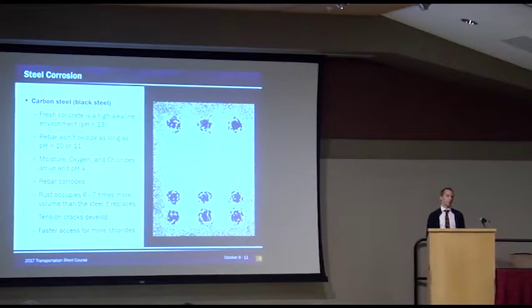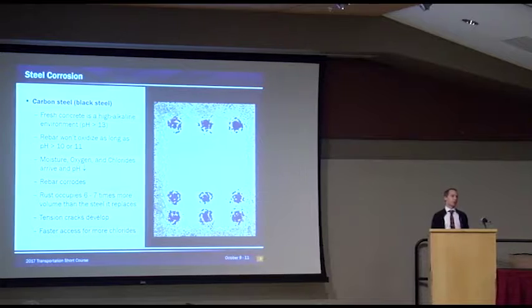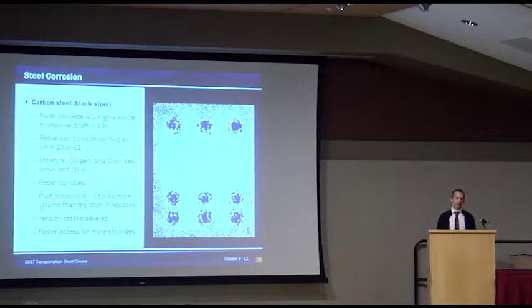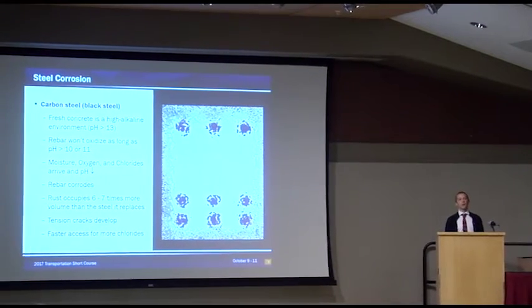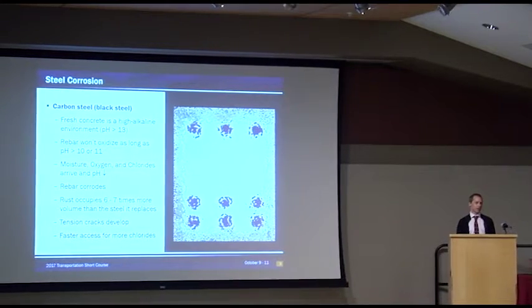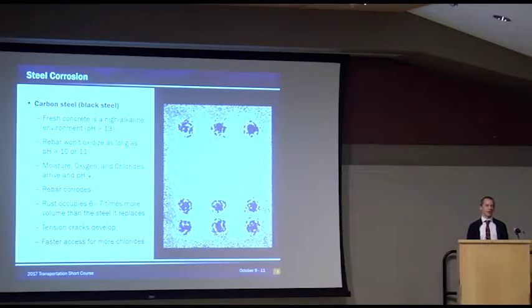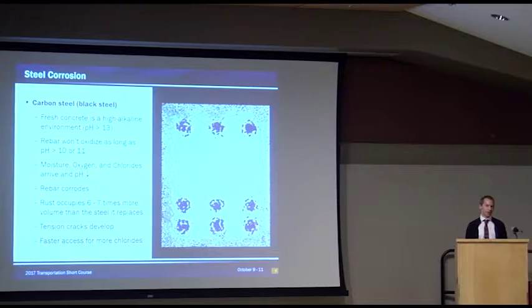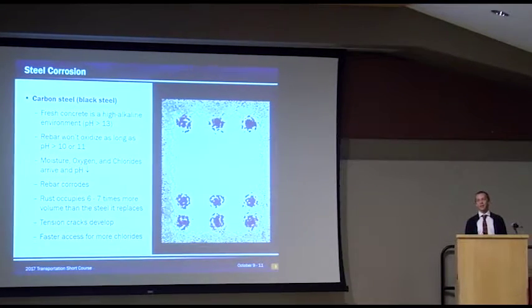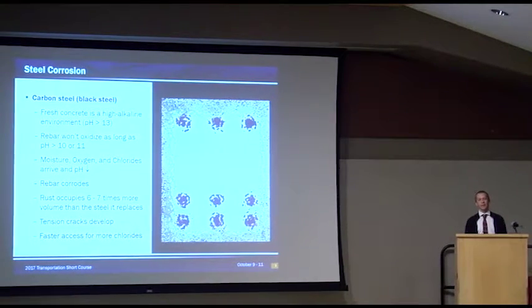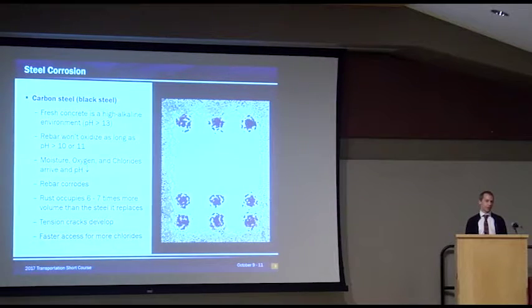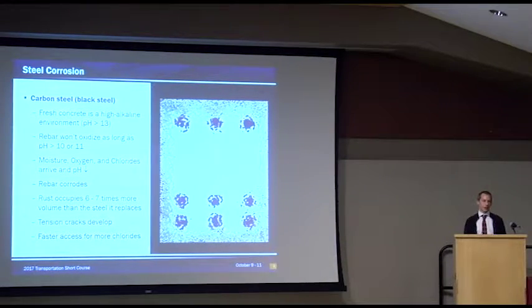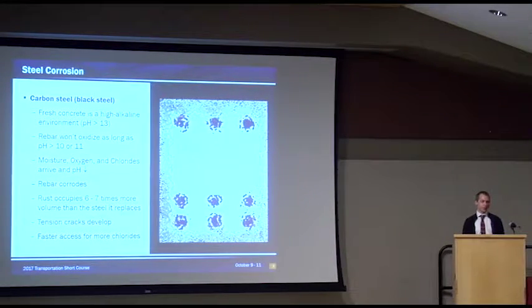The real problem here is when it corrodes, the corroded material begins to take up about 7 times more volume than it used to. So we're basically inflating a bunch of little tiny balloons inside the concrete. This causes tensile stresses, opens up cracks. More chlorides now get to the rebar, and now we're talking about section loss and real capacity issues. So that's what we're dealing with.